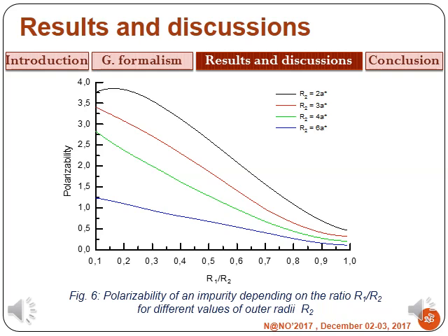For large values of the ratio R1 on R2, a thin spherical layer, the geometric confinement is important and the wave function of the electron is very localized. The electric polarizability of the impurity becomes less important and is relatively insensitive to the outer radius R2 of the quantum dot quantum well. For low values of the ratio R1 on R2, a large spherical layer, the effect of the electric field predominates. The polarizability is strongly dependent on the size of the quantum dot quantum well. We note that the polarizability decreases as the ratio R1 on R2 increases.